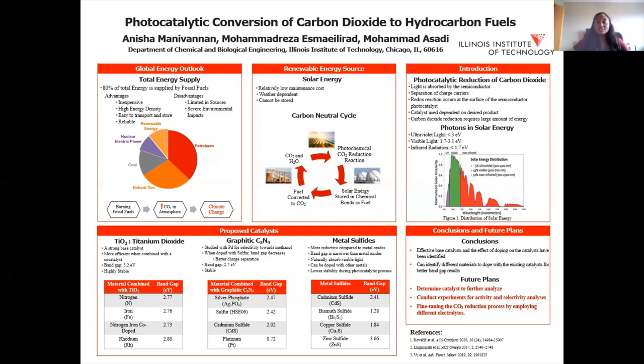There is also uncertainty in the product selectivity of each catalyst, as there is not a clear mechanism that occurs. Carbon dioxide is extremely stable, so in order to reduce it, a large amount of energy is needed. 43% of solar energy is distributed in the visible light region, so the most effective catalysts need to have a band gap between 1.7 and 3.1 electron volts to capture that energy.